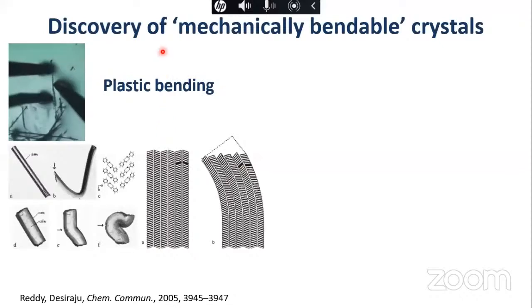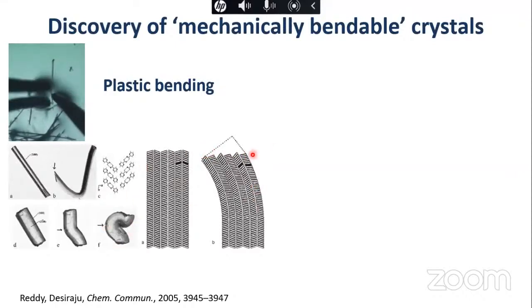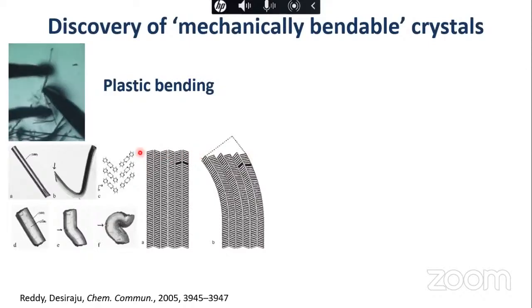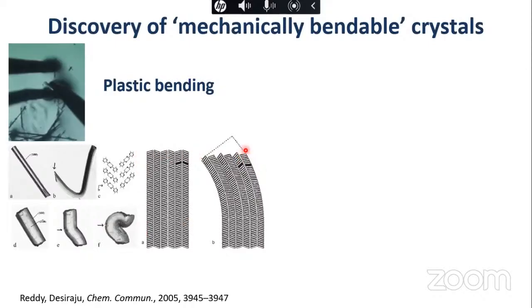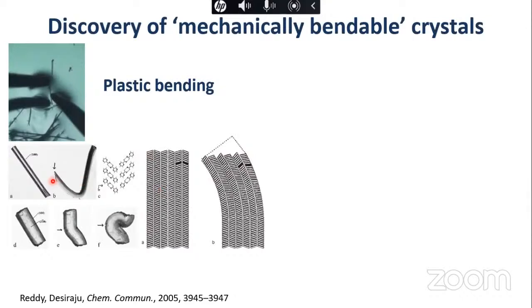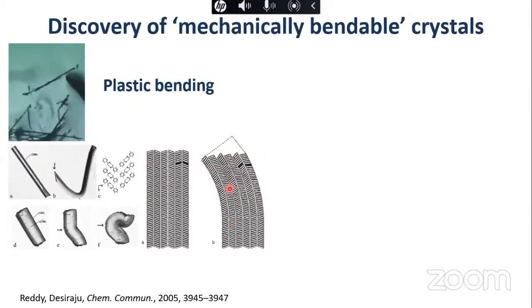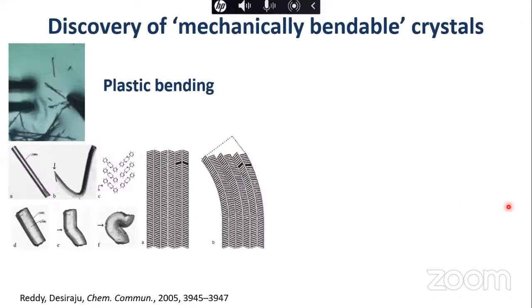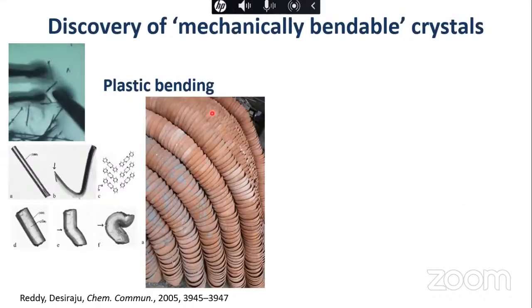The crystal is growing in this direction, and then you push from this side. So these layers slip one over the other, and then they basically bend. When they bend, this plane here, which is 90 degrees, changes to a different angle. The way you see it here, earlier it was something like this. After bending, you will have it. So that is how you can explain it in terms of the crystal bending. You have weak interactions, and then you bend, then you will have something like this.